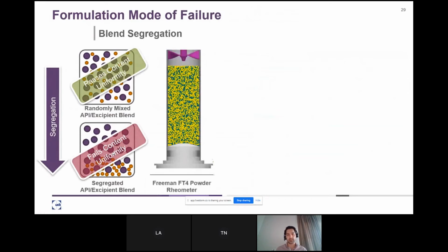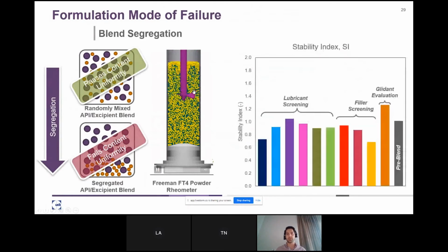One of the techniques that we are using is, for example, the FT4 powder rheometer, where you have an impeller that rotates, penetrates into the powder bed, and then moves up. We repeat this test multiple times, 10 or 20 times, and then we measure the work that was required for this impeller to move through the powder bed.